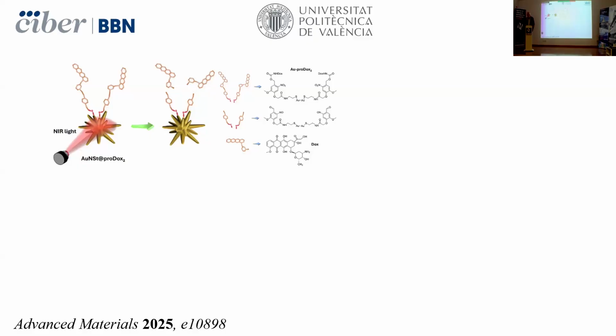So we are not working only with mesoporous nanoparticles. We are also interested in that concept. So we are using now gold nanostars because, if you irradiate a gold nanostar with light, there is, as is well known, a high accumulation of electromagnetic field in the tips of the star. What is less known is that this accumulation of electromagnetic field has been reported to be able to break chemical bonds. So then we decided to use the gold nanostars and anchor a molecule that contains doxorubicin and is attached through different bonds to the star.